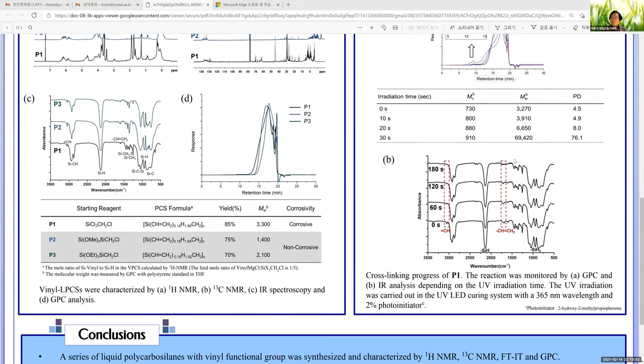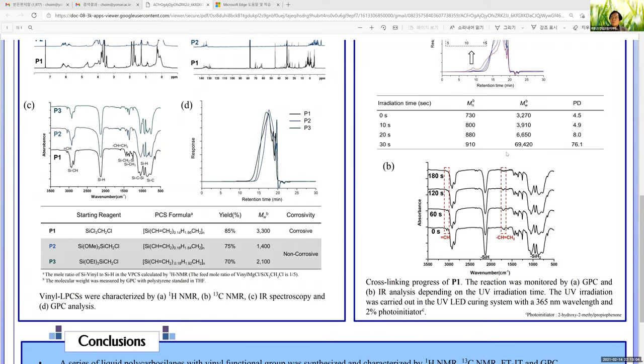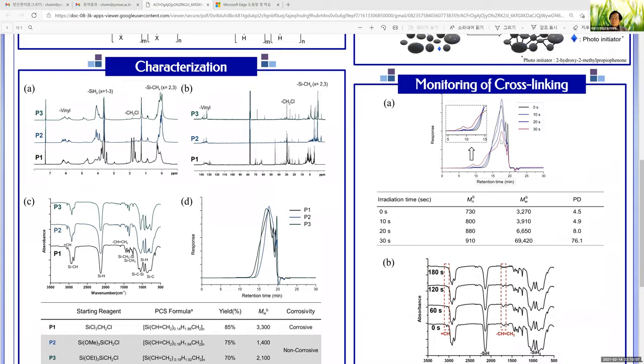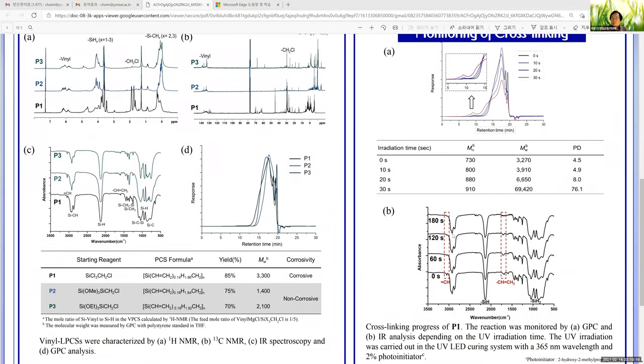And this process was followed not only by GPC, but also conveniently by using the IR. And you see here, a little over 3000 wave numbers, the vinyl CH frequency has decreased as you have a longer irradiation time. And also here is another very typical IR stretching for the vinyl C=C double bond.